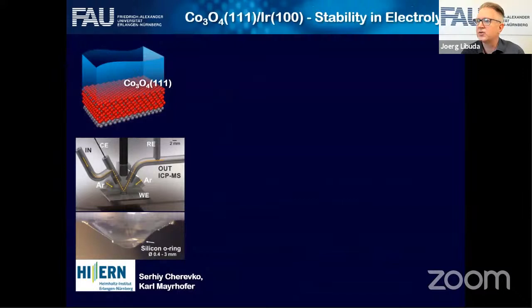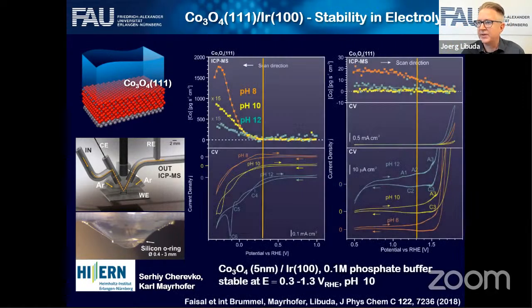So you can also do that with these thick cobalt oxide layers. I showed you that you can make these films, then bring them into an electrolyte and bring them back and show that they are still there. Now, of course, the question is, do these systems dissolve to some extent? And you can measure that with this mass spectrometry experiment. So we have done that at different pH as a function of the potential.